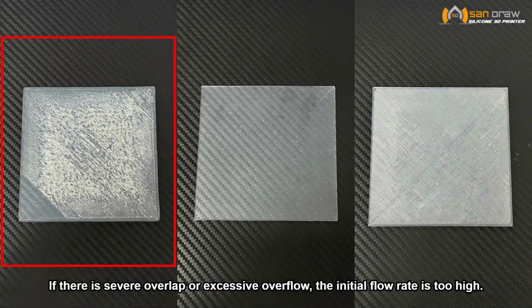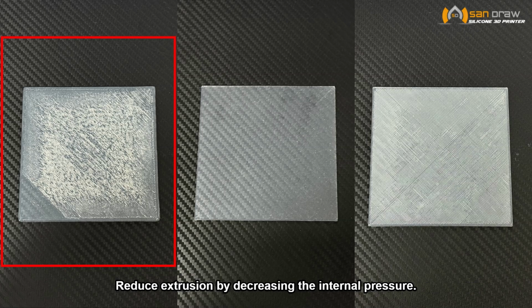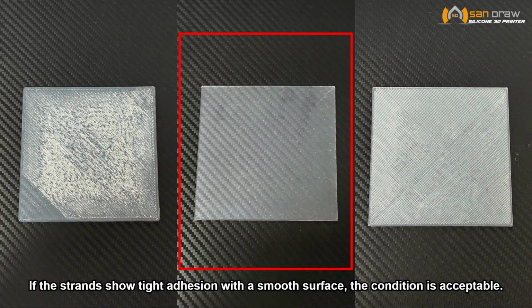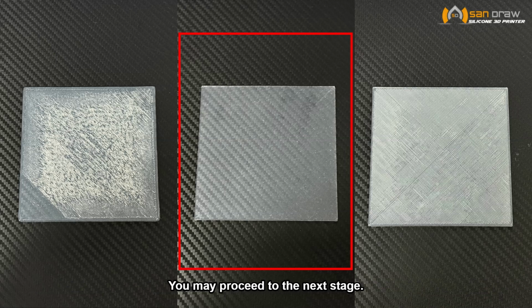If there is severe overlap or excessive overflow, the initial flow rate is too high. Reduce extrusion by decreasing the internal pressure. If the strands show tight adhesion with a smooth surface, the condition is acceptable. You may proceed to the next stage.